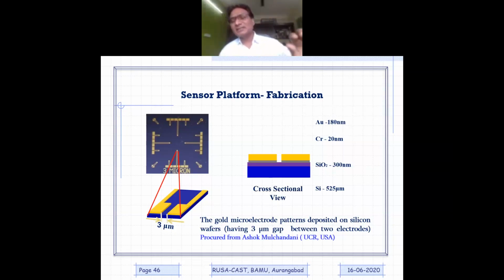However, there are certain VOCs for which CNT responds very poorly. For those analytes it is going to have very poor sensitivity as well. And most importantly, there is a dearth of efficient methodologies for incorporation of CNTs in the sensor matrix. So these are some of the issues you will have if you are really working with CNT material as a sensing backbone in your matrix.